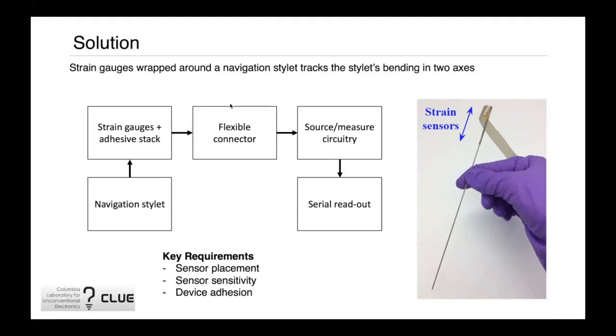These sensors consist of patterned silver on flexible PDMS and are placed on a 1.3 millimeter diameter navigation stylet using an adhesive stack. The signal readout is performed by connecting a flexible heat seal connector, which is also connected to source measure circuitry. Overall, the key requirements for our device are precise sensor placement, high sensor sensitivity, and good device adhesion to the stylet.